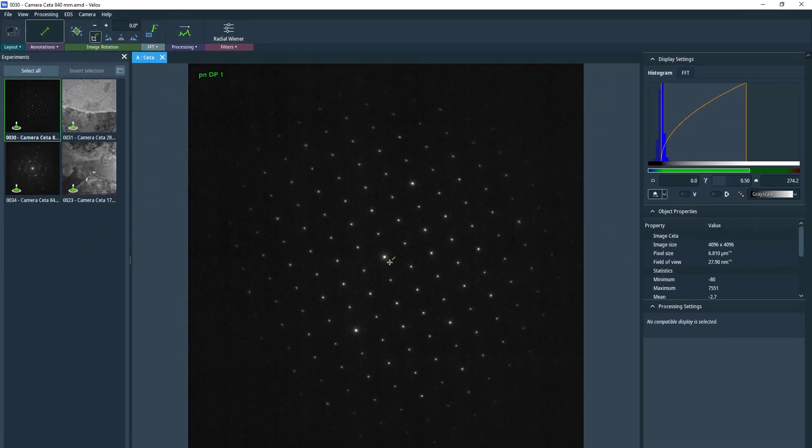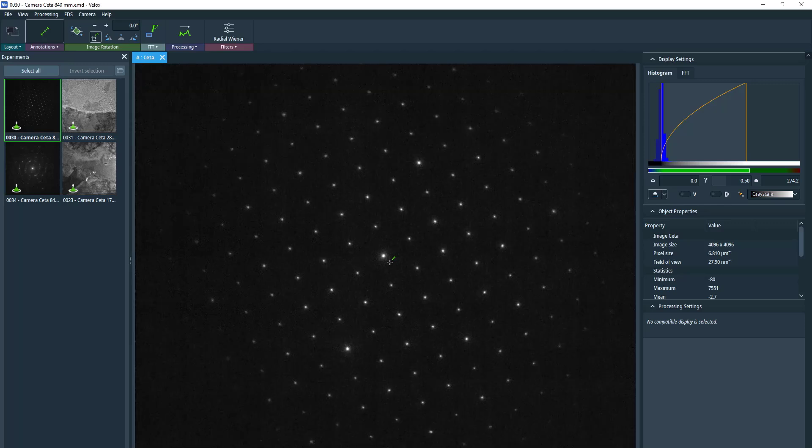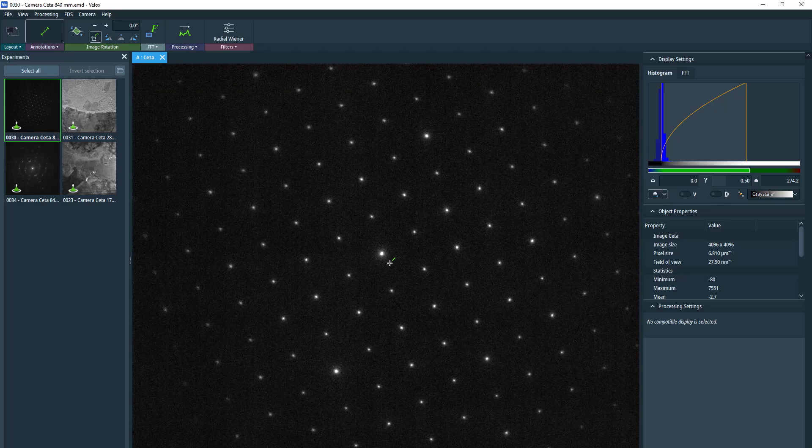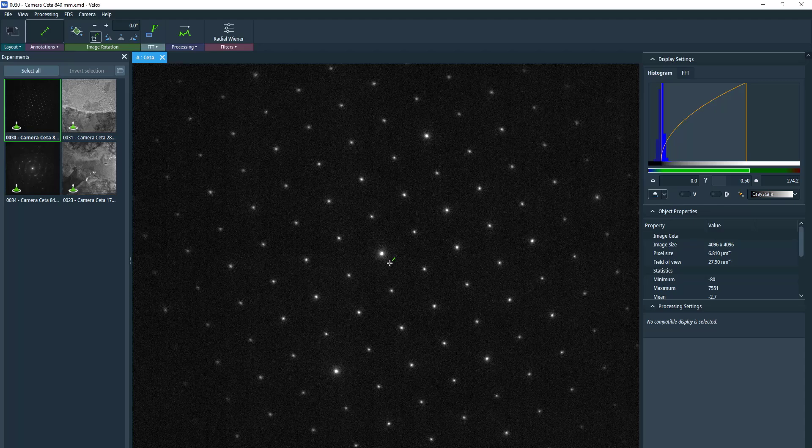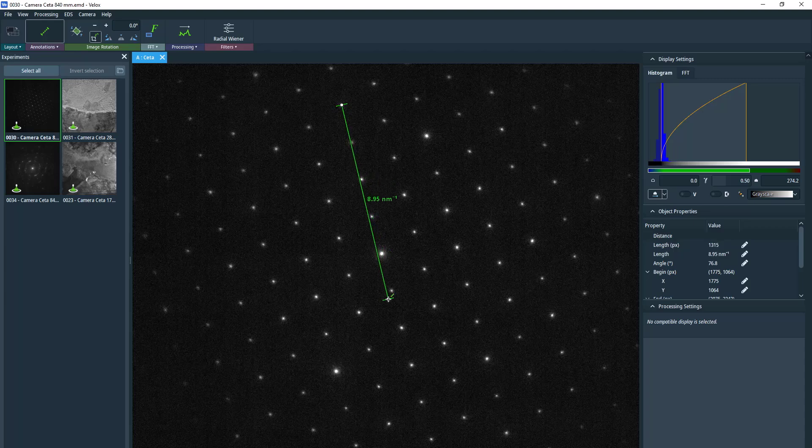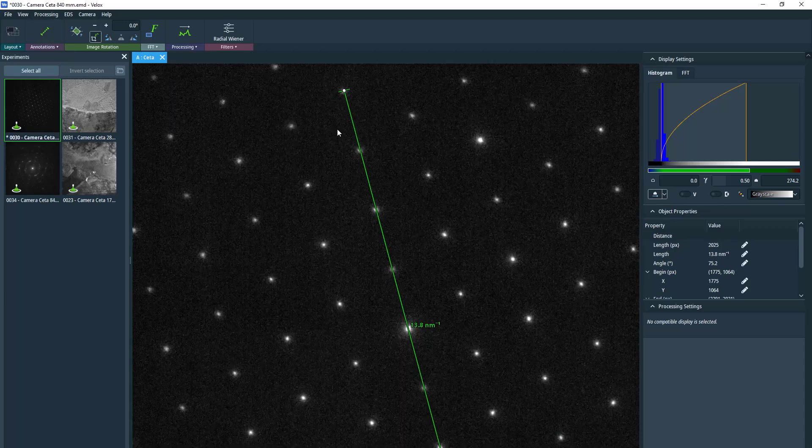I'll talk a bit about what those are in a second, but the important point is we want to measure the distance for these different lines through the central transmitted spot. It's more accurate if we measure multiple spots and then divide by the amount of spaces that we measured through. In this example I've passed through four spots and then four more, so this is a total of eight spacings.